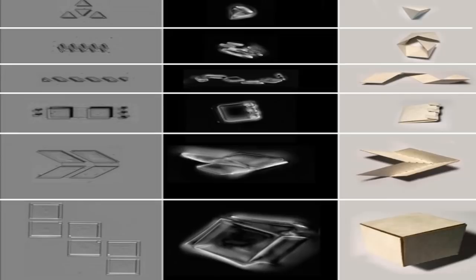In the case of graphene and glass, the bimorphs also fold in response to chemical stimuli by driving large ions into the glass, causing it to expand. Typically, this chemical activity only occurs at the very outer edge of the glass when submerged in water or some other ionic fluid. Since their bimorph is only a few nanometers thick, the glass is basically all outer edge and very reactive.